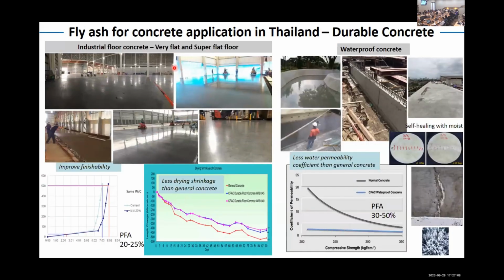Also, as I mentioned, for the floor, for waterproof concrete, we found some effect from the fly ash: when the concrete cracks and is fed with moisture, in a moist environment, after that it can heal itself when the moisture comes to the structure. So it's the effect of fly ash as well. This one just wants to show you what applications we use.